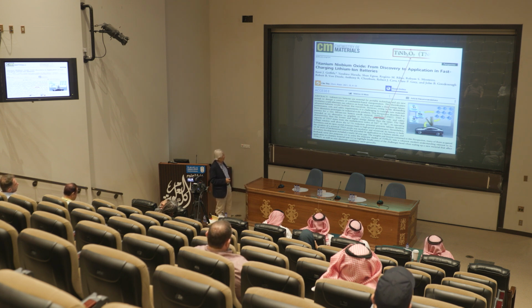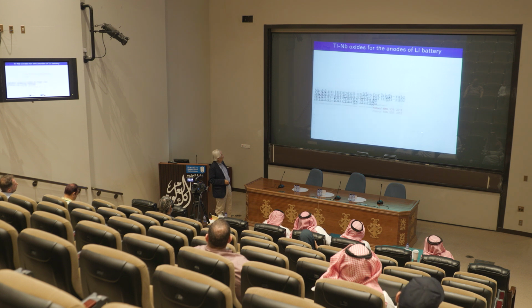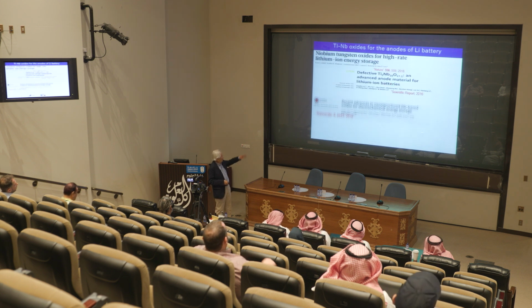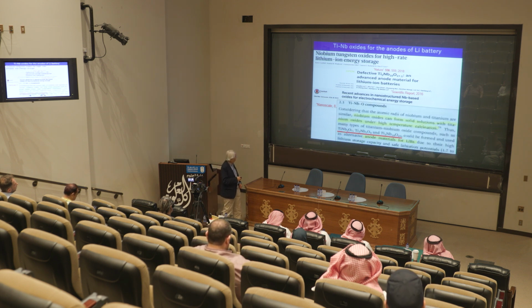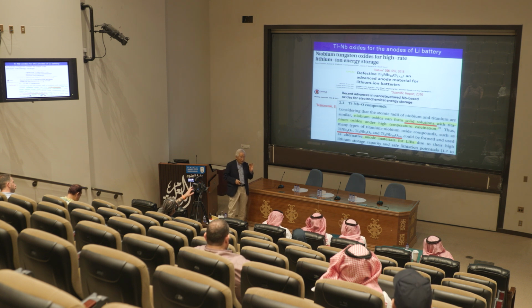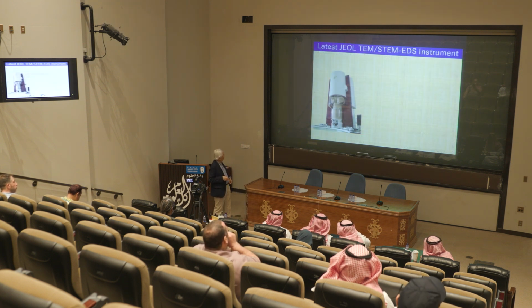Yeah, there are many reports about this material for lithium, but here the titanium niobium oxide is the one being discussed. So I had this one, Ti2Nb10O29, 50 years ago. So I started to check this material, and these people say it is a solid solution, the titanium niobium oxide, a ternary oxide, but they don't know exactly how titanium and niobium are arranged. X-ray cannot distinguish. So then this is a good subject.